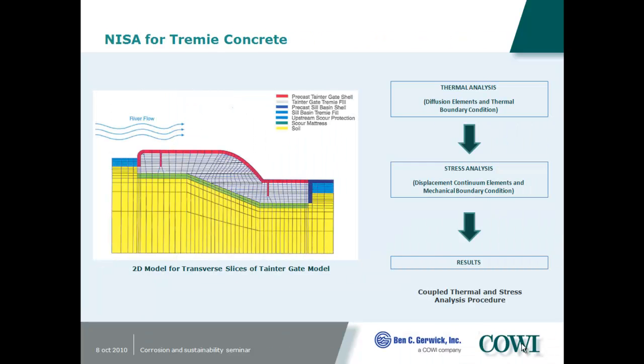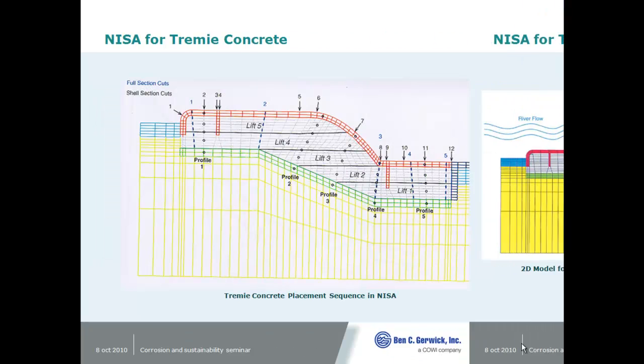So this gives you an idea of one of the major reasons for using such a low cement content was that we have very thick placements of Tremie concrete here. This is, I think, close to 60 feet from here up to here. So there was a large amount of fresh concrete for a massive pour. It's important to control the thermal stresses.